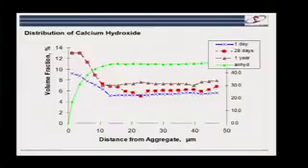Because we've got less anhydrous grains here, we've got more space, and the fact we've got more space means that actually this favors the precipitation of calcium hydroxide in this zone. And this is quite good because we had more space to start with, more calcium hydroxide has formed in this space, so it tends to cancel out to a large effect this extra porosity.